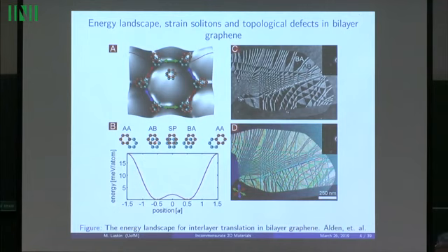Let's say this is the B atom of the top layer, sitting right in the center of the hexagon. So that's real good. It's as far as it can be from any of the blue atoms. So in this configuration, 3 of the 6 atoms in the hexagon are sitting right in the center of a hexagon. That's the best possible arrangement of one layer on another, energetically.